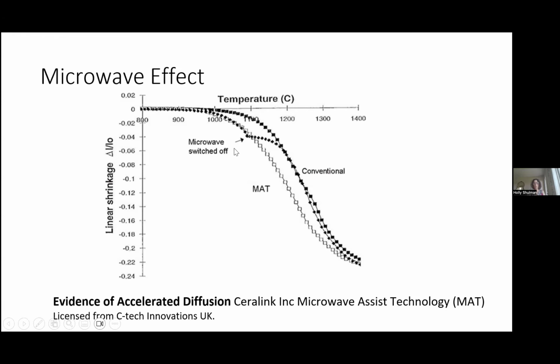When we switch the microwave on, so this is actually CTech doing this, you can see that at a lower temperature, measured on the dilatometer, we're getting shrinkage. So that shrinkage is caused by enhanced diffusion. So this is some really good evidence. And then a third sample, so this really, it shrank at a lower temperature reading.